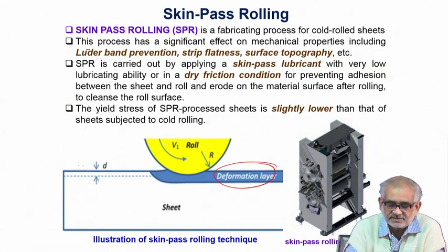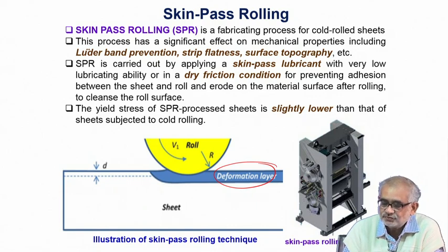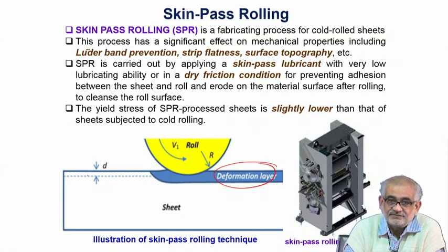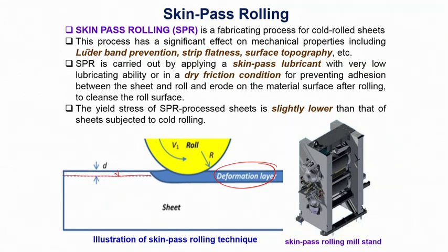If you have a certain stock of finite thickness and pass it through two rotating rolls, and if the material has a thickness slightly greater than the gap between the rolls, there will be deformation. If the gap is nearly about the same as the thickness of the material, the deformation layer will penetrate only a skin depth from the surface. That kind of rolling with controlled deformation is called skin pass rolling (SPR).